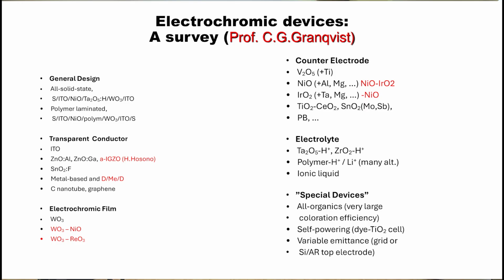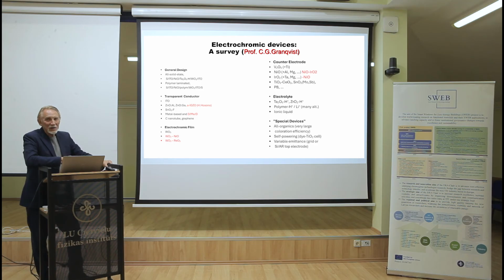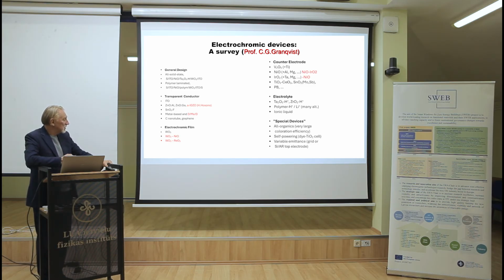At this moment, the structure is published in many books, and the review discusses the structure, some problems, and the state of the art on the application of electrochromic materials. It starts from transparent conductive oxides, which must not be indium but must be much cheaper than indium, for example zinc oxide with aluminum or other cheaper oxides. The electrochromic materials have a problem especially with color, and we have also developed mixed oxides to change the color and properties, like tungsten nickel oxide and so on.